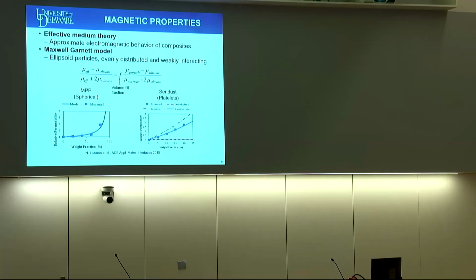And we wanted to understand what the resulting magnetic properties are. In this case, because we are just stirring them randomly into the material, we don't have a definite idea of exactly where each particle is found. And so the way that we modeled this, or the way that we understood this, was to apply something called effective medium theory, where we are trying to estimate the overall behavior of the composite by making certain assumptions about the distribution of the particulate. In this particular case, we have roughly ellipsoidal particulate. We're assuming we've mixed them fairly evenly within the composite, and that by magnetic standards there's a relatively low density. And so we want the mechanical performance to remain dominated by the silicone elastomer, and we can assume that they're weakly interacting.